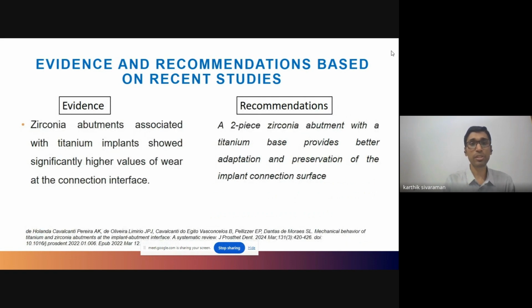Now, a few recommendations are based on evidence from another study which was published in 2024. There is a greater tendency for clinicians to use a zirconium abutment along with a titanium implant in the anterior region. They feel that it will combine the advantages of zirconium with titanium. It will give a better set of aesthetics. But there is evidence to show that zirconia abutments associated with titanium implants showed significantly higher values of wear at the connection interface. Now, what is the reason for that?